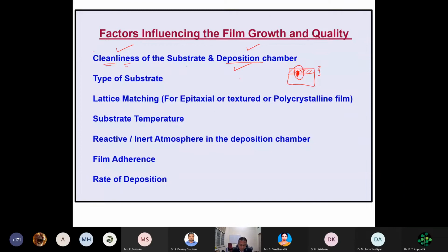Suppose today I am using a low melting point material to be deposited. If I don't clean the inside of my chamber properly, tomorrow somebody is coming and using a high vaporization point material. Say, for example, if they keep their substrate temperature around 800 degrees centigrade, then yesterday's material which was deposited will see a high temperature in that region, and it will start evaporating once again from the walls of the chamber sometimes, or from near the place where you are keeping your substrate, and then they will go and contaminate your substrate.